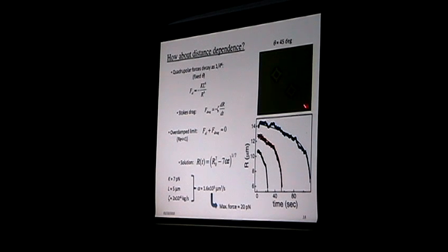And so basically what we do is take these particles at some separation, release them, and track them coming together. And over the course of this motion, the equation of motion is the balance of this driving elastic force with a Stokes drag. The system is highly overdamped, the Reynolds number is extremely low, so we can neglect inertia. And you can solve this equation. It's pretty simple. It's a power law force, so you get this power law time dependence. And so this is data for three pairs of squares coming together from three different initial separations. Okay, and this works very well.